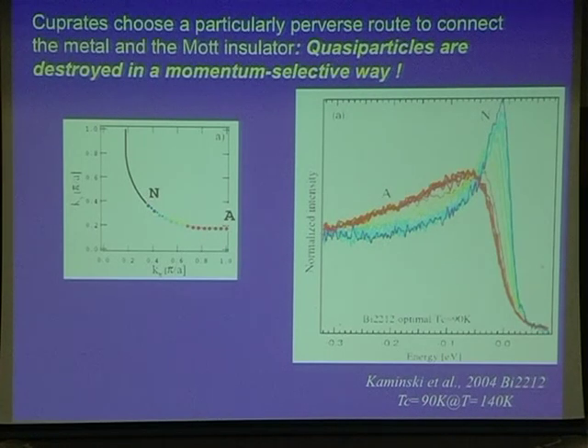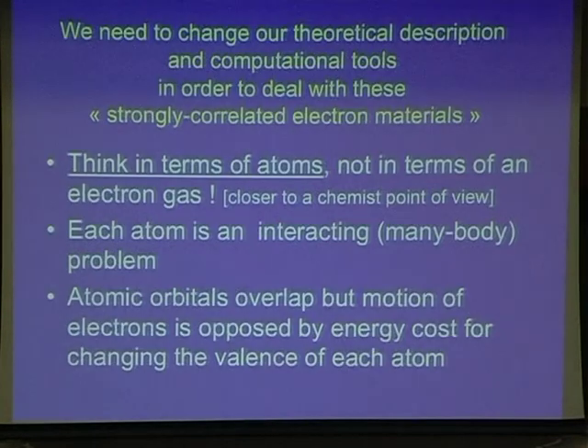And you see that these materials are particularly perverse, because what they do is that they have a sharp quasi-particle peak there, but they have no quasi-particle peak at all there. So it's not only that Landau theory of conventional quasi-particle excitation fails, it fails in a way which is momentum selective. It fails badly here, but it kind of survives there. That is the problem. This is one of the most perverse problems that is brought to us by these materials.